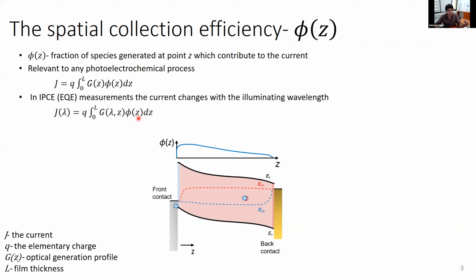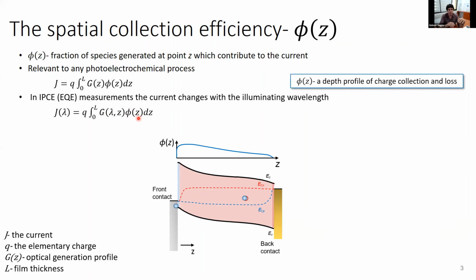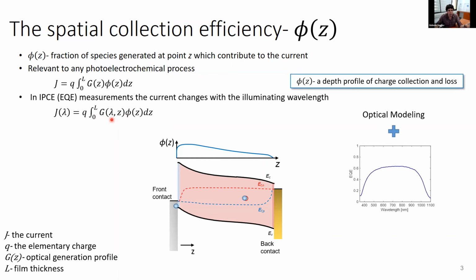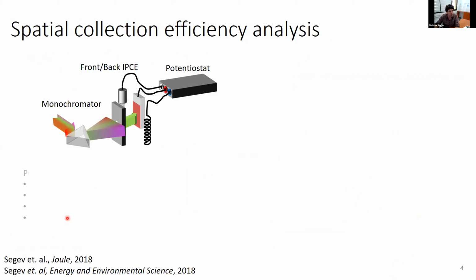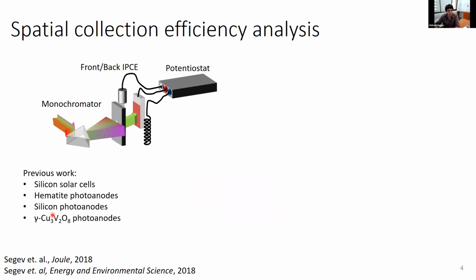So just to sum this up, the spatial collection efficiency can be thought of as a depth profile for charge collection and loss in the device. And the way we find it is we use optical modeling to find the optical generation at every point for every incident wavelength. We take EQE measurement or IPCE, same thing, and throw this into a numerical algorithm that will spit out the spatial collection efficiency. So this is something that we already did several times on several different material systems, and we're able to get pretty interesting